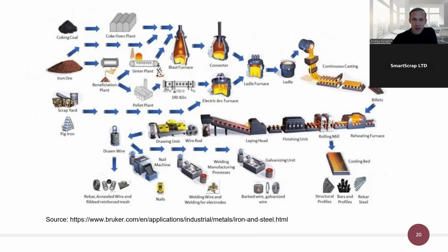So another route is electric arc furnace. For electric arc furnace, we have as a raw material scrap, pig iron, and DRI. DRI is produced from iron ore. We see here again, iron ore goes to beneficiation plant. After beneficiation plant, we have iron ore concentrate. Then iron ore concentrate goes to pellet plant. We have pellets, and pellets go to DRI kiln to produce direct reduced iron. And all this material as a DRI, scrap, and pig iron can be used in electric arc furnace.